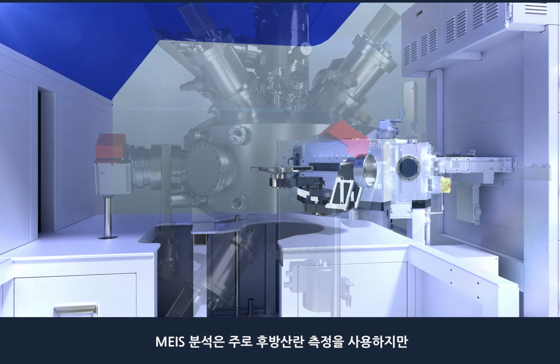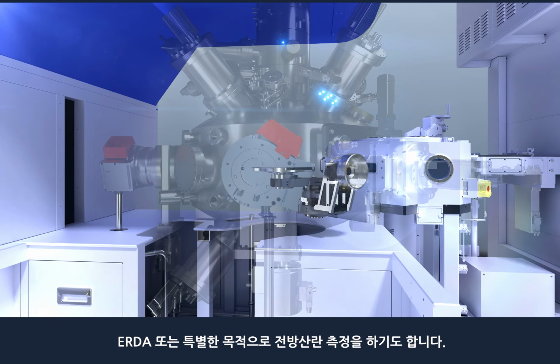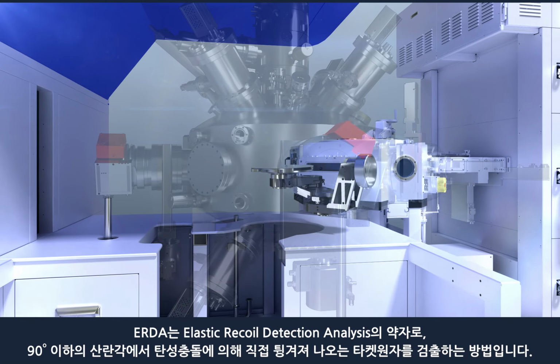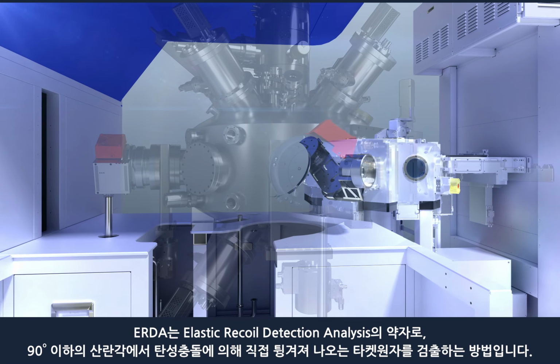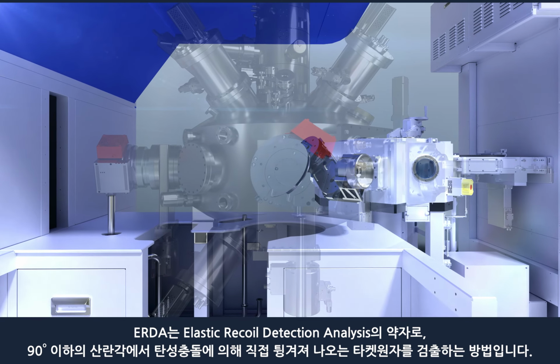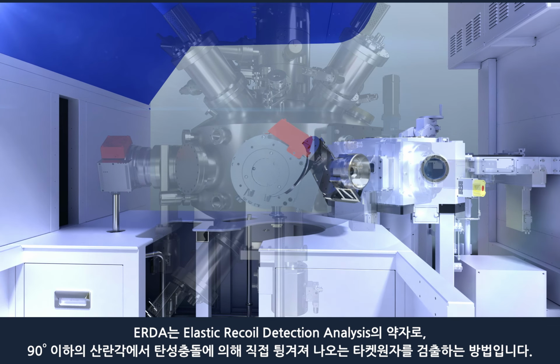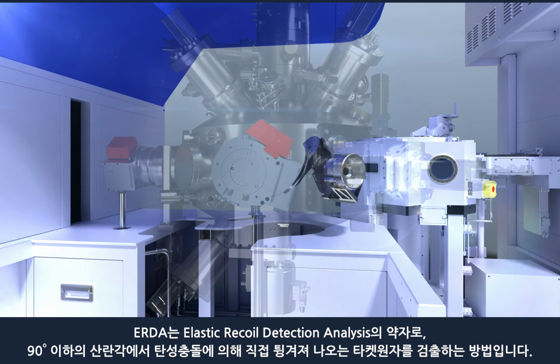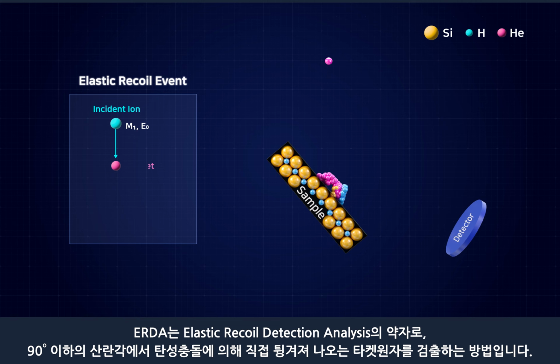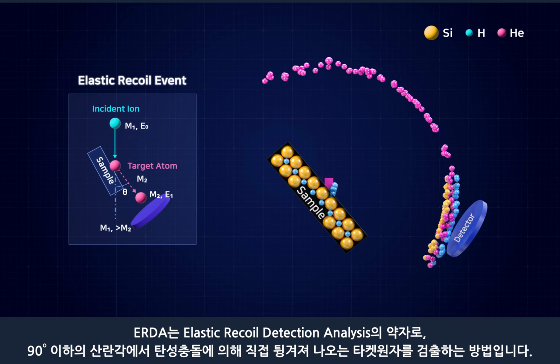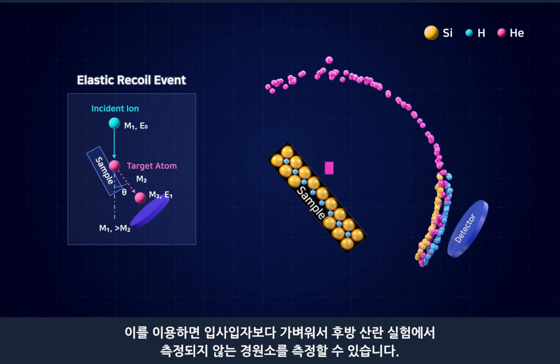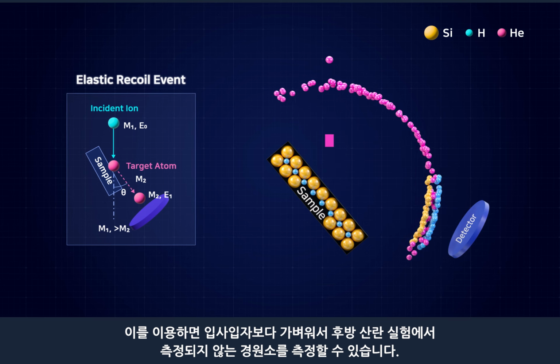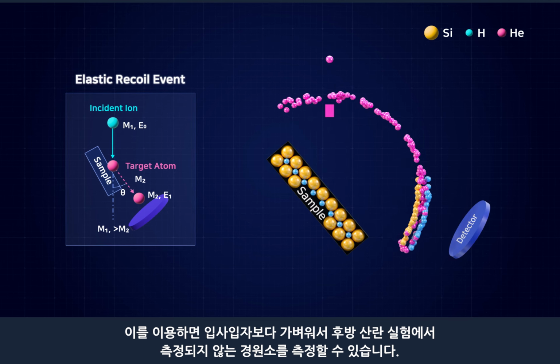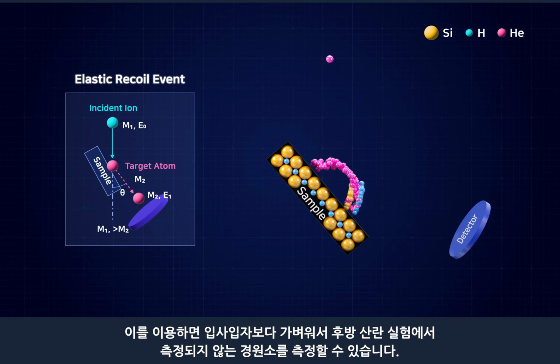MEIS analysis mainly uses backscatter measurements. ERDA or forward recoil scattering measurement for special purpose are also used. ERDA stands for Elastic Recoil Detection Analysis. This method detects target atoms recoiling directly at scattering angles of 90 degrees or less via elastic collisions. This method can be used to measure atoms lighter than the incident ions that are not measured in backscattering experiments.